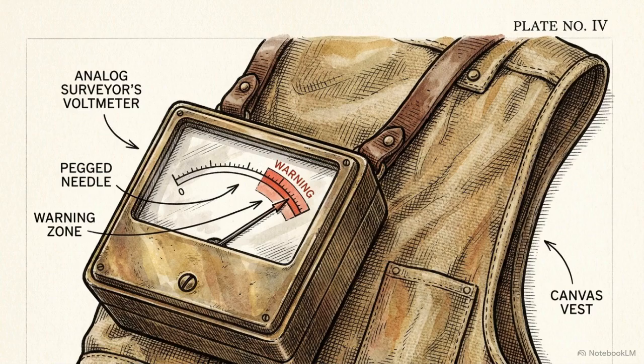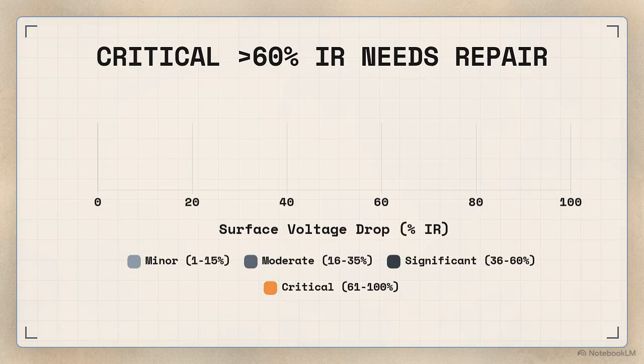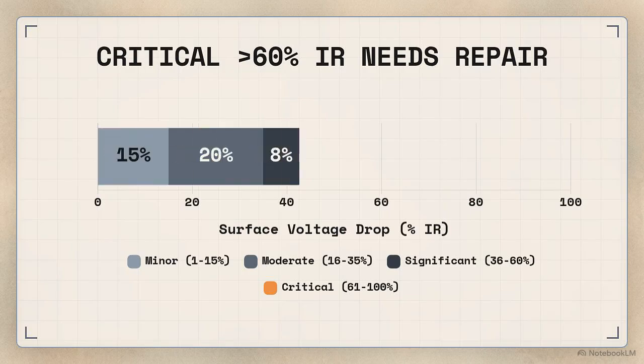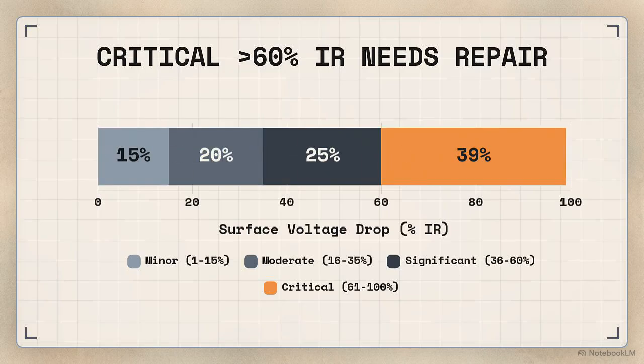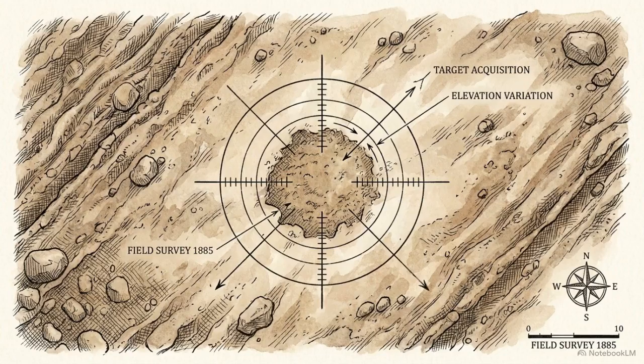Surveyors measure this surface voltage drop using a metric called %IR. A higher percentage indicates a larger current draw. For example, a 61 to 100% IR drop indicates severe coating damage that requires immediate attention. The DCVG survey effectively translates an invisible subterranean chemical reaction into a quantifiable, targetable coordinate on the surface.